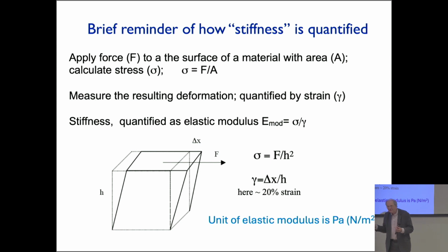And for most simple materials, rubbers and gelatin and things like that, the volume doesn't change very much and the mechanics are fairly simple. So if you measure the resistance to shear deformation, it's similar or calculable from the resistance to uniaxial deformation. For tissues, that turns out to be not true. The composition is much more complicated.